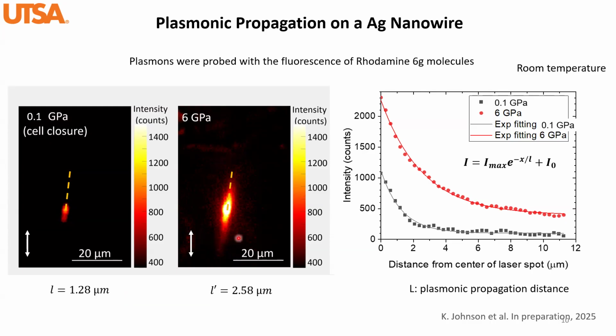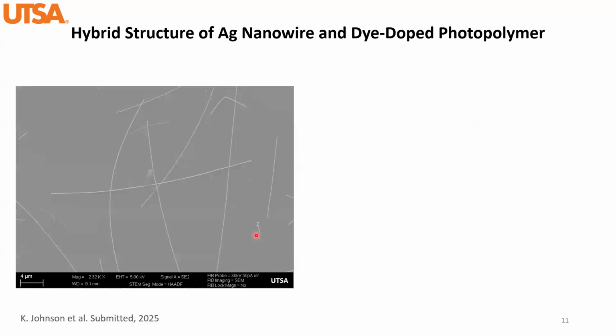Just by probing the surface plasmons, this probing activity itself is causing some loss, because you need energy to be transferred from the surface plasmons to the dye, right? So we thought about an improved configuration of this experiment. We trap the dye molecules inside a photopolymer. We created a tiny little polymer bridge doped with dye molecules. So we don't have dye molecules everywhere, they are all trapped in this photopolymer.